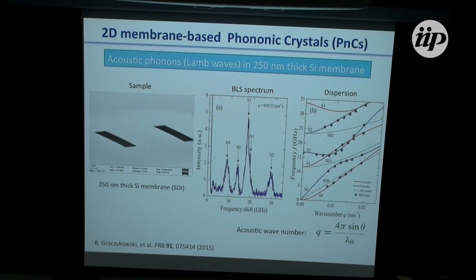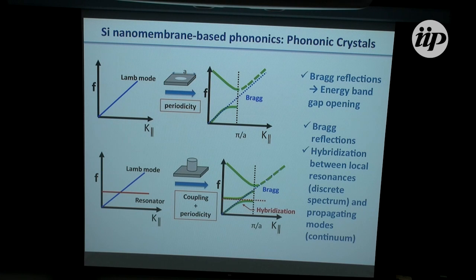This is a relationship we use to obtain points different from zero, from Q equals 0. Okay, so this is our starting material. Then we decided to fabricate two types of phononic crystals. One, where we would be modifying the periodicity by introducing holes. So we would then have Lamb waves that would travel on the membrane, traveling in a holey structure. This periodicity would open gaps due to Bragg reflections.